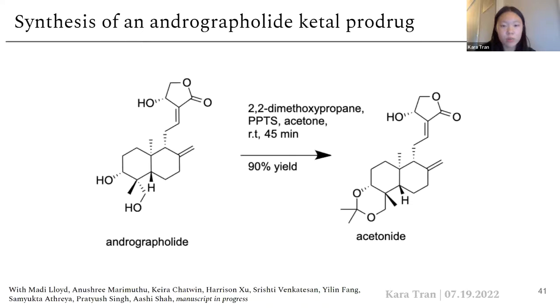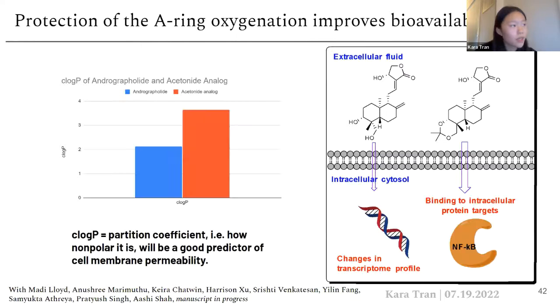So this is the mechanism of one of our analogs, acetonide, which is a ketal prodrug that was thought to be significant. This is because when you look at the C log P of acetonide compared to andrographolide, acetonide has a higher C log P, indicating that it is more hydrophobic, which we hypothesized would improve its cell permeability.